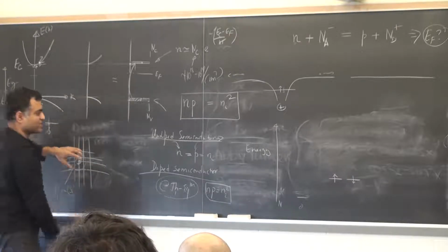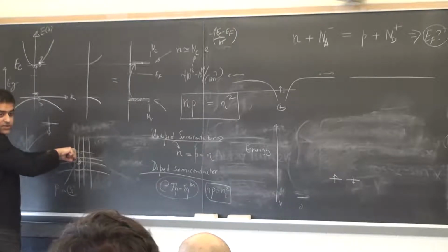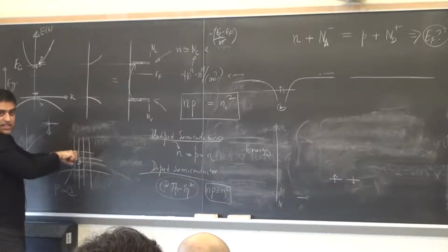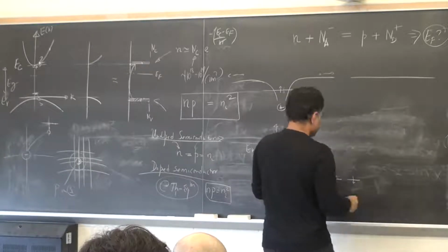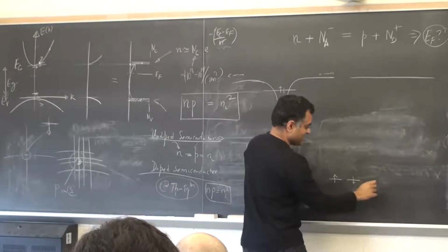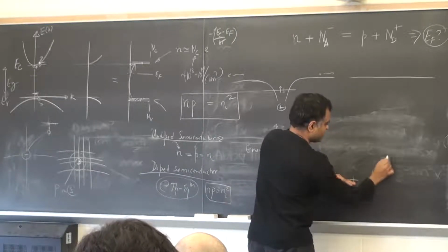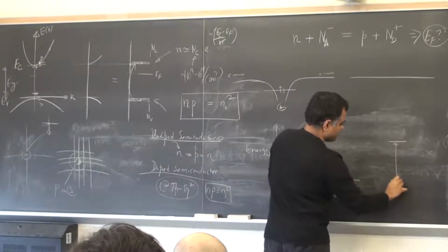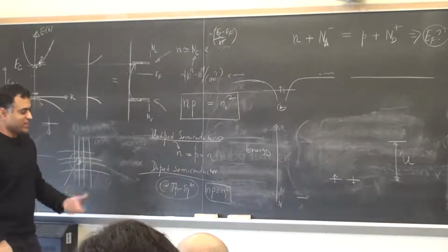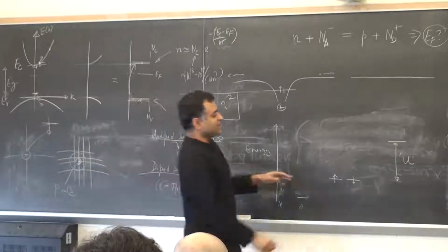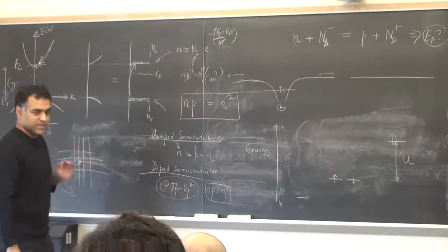And so if I want to put another electron in it, these two electrons are very close to each other in space, in real space. They are not waves. Does that make sense? As a result, there's a huge amount of Coulomb repulsion. There are two like charges, so there's a huge amount of Coulomb repulsion. Therefore, if I want to put two electrons, I can't have the same energy as these states. The energy will float up to a certain value, and that's typically called a Hubbard energy, or U. And this is a many particle physics picture. Basically, you can't put two electrons in the same state, and if you were to put two, then the energy cost would be much higher. That's the meaning of it.